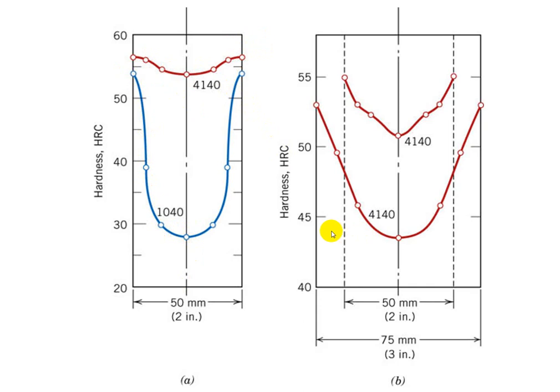Next thing is comparing the same alloy, two different sizes. You realize that the bigger the diameter, it becomes somehow less hardenable because the bigger the diameter, more heat dissipation, lower cooling rate, there is a chance that you will not get the same structure. Even at the surface of the same 4140, you can see the hardness is higher than here. You might say wait a minute, they are all put in the water, they are cooling at the same rate, but they're not the same rate because more heat would be dissipated from the specimen with a bigger geometry and diameter.